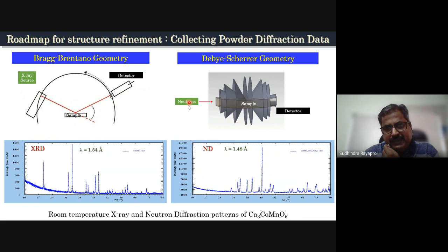In the case of neutrons, mostly they use what is called the Debye-Scherrer geometry, which means it's a transmittance geometry. Neutrons pass through the sample and scatter all around, and we put detectors on this cone and measure the diffracted pattern.